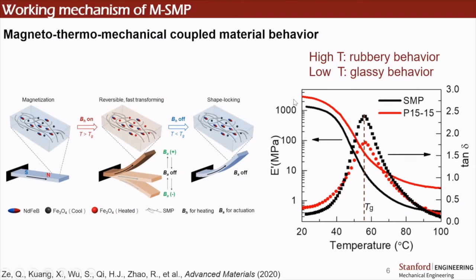Now if we increase the temperature of the material, once it goes across the glass transition temperature, it will drop its rigidity significantly. Eventually, at a temperature around 80 degrees C, you can see the material drops even below megapascal level. So it shifts 3 orders of magnitude in terms of the Young's modulus. Through this transition we can tune the rigidity of the material, and combined with the shape morphing capability, we have a composite that gives us deformability. In the meantime, by tuning the rigidity, it can potentially give us enough force to interact with other objects.